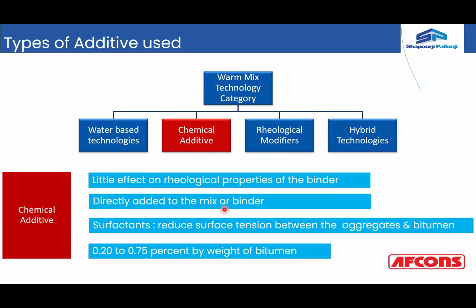Now, when you talk of the different types of technologies, there are water-based technologies, there are chemical additives, there are rheological modifiers, and there are hybrid technologies available in the market, which will turn your hot mix asphalt into a warm mix asphalt. And when we talk of warm mix asphalt, please remember that your production temperature needs to be reduced by 30 degrees relative to conventional hot mix temperatures. Unless you reduce the temperature, you will not be able to achieve the complete advantage of using the warm mix asphalt. When you talk of chemical additives, they have little effect on the rheological properties of the binder.